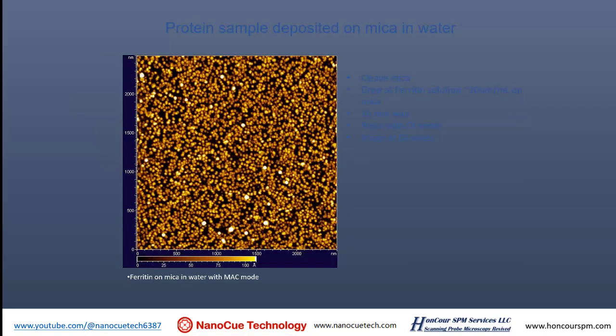So this is an example of using the charge to prepare a good sample. This is a standard sample. If you want to practice your AFM imaging skill or diagnose any problems using AFM, I suggest you use this sample. This is called ferritin. You can buy these ferritin samples from Sigma Aldrich, and it's very easy to prepare because those ferritins are very strongly positively charged. So if you drop a ferritin solution on the surface of mica, rinse it right away, you can image them in water, and it's a very nice sample.